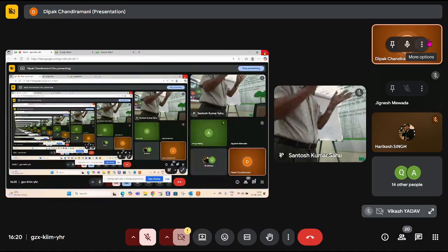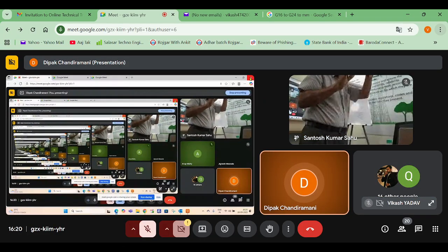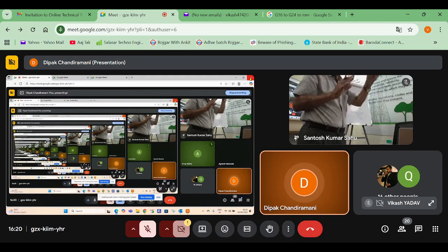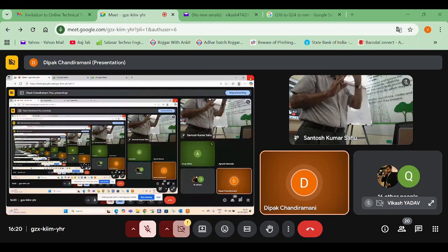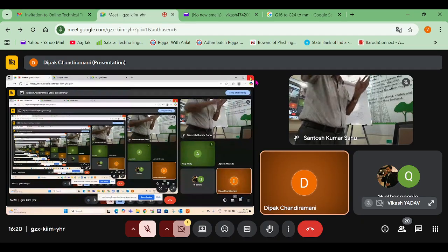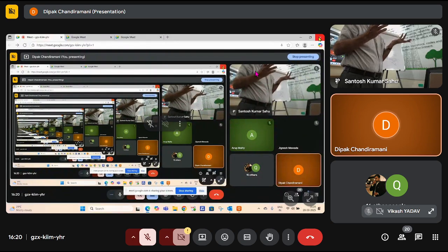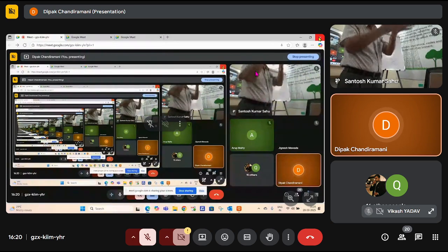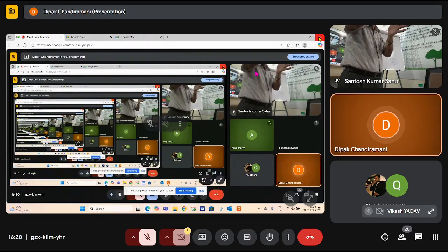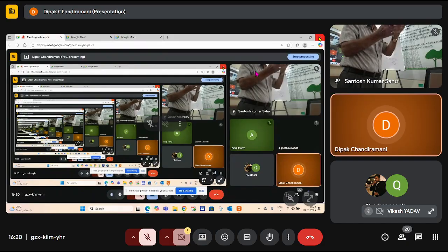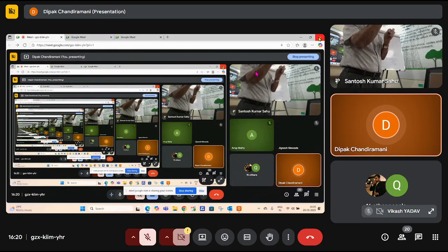Now, what is the gauge doing? It is sending a pulse of sound into that material. Based on the velocity of sound in the material, you are getting a correct or incorrect result. So it's not universal that if you put it anywhere, it will be correct. The velocity changes. So you have to again validate it by taking a block of material which is near to the thickness you are trying to determine, and verifying that it is still showing correctly, because now I can measure it.